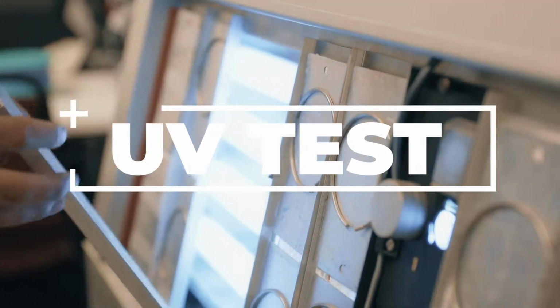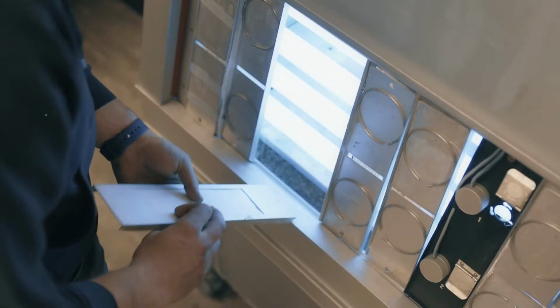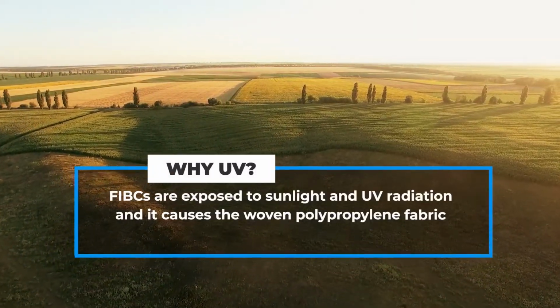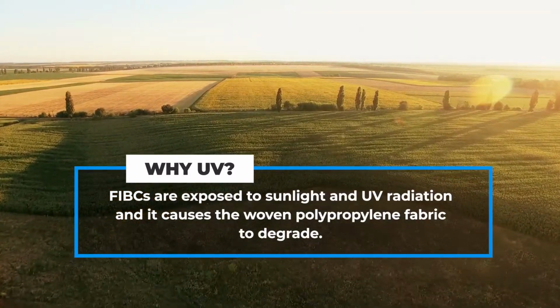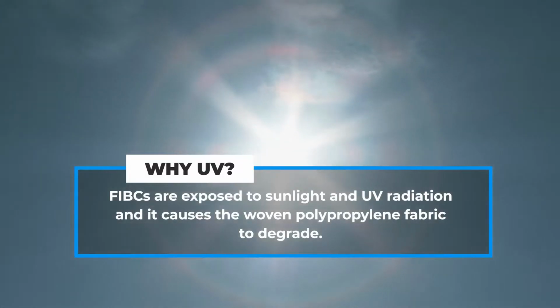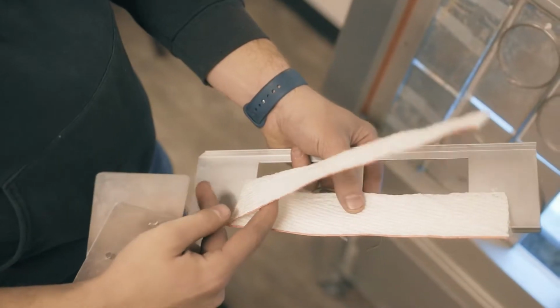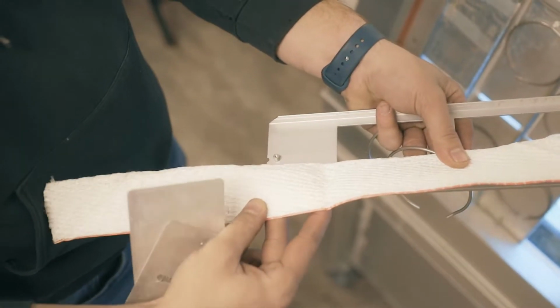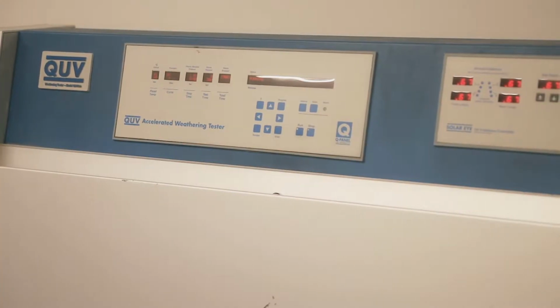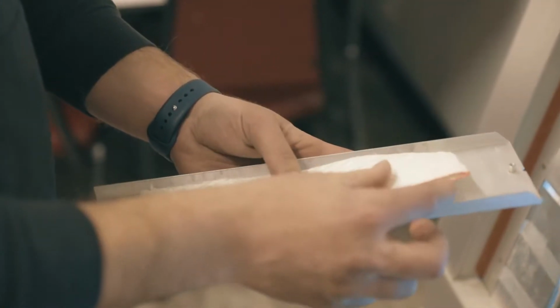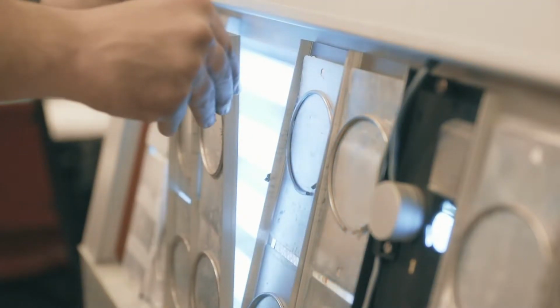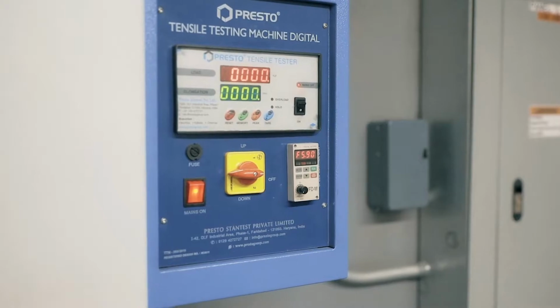UV tests help us determine if the woven polypropylene has enough UV resistance to meet the ISO standards. Why? FIBCs are exposed to sunlight and UV radiation, and it is causing the woven polypropylene fabric to degrade. Based on the ISO 21898 standard and done on a QUV accelerated weather tester. Test the sheet of polypropylene fabric by exposing it to a fluorescent UV light for a minimum of 200 hours and alternate between 8 hours UV radiation and 4 hours of 50 degrees Celsius condensation. Then strength test on the tensile test machine.